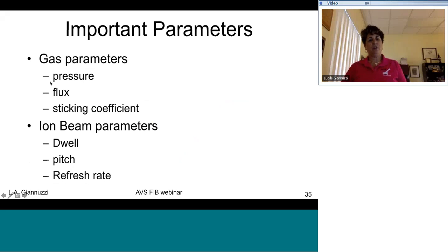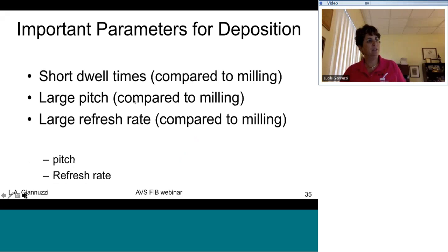In general, you can't change these. These are vendor specific. In some cases, you can change the pressure by just changing the temperature of the gas. But the ion beam parameters are something that the user is going to have to pick correctly. And this is generally the dwell, the pitch, the refresh rate, and of course, what ion beam current do I even use for that particular pattern.